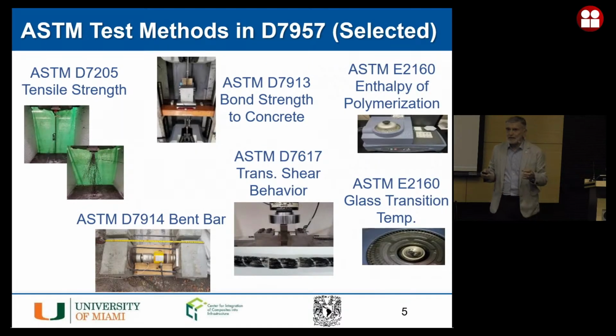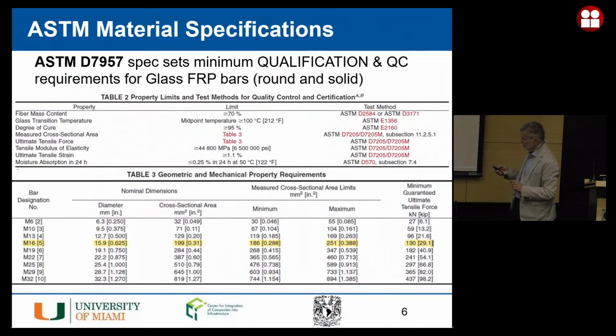In terms of quality assurance, if we follow this ASTM D7957, we run tests that are different from the ones that you might see in the laboratory. I'll give you an example of only one, this E2160. This is to measure the enthalpy of polymerization. What are we talking about here? What we need to do is to make sure that the resin is fully polymerized. If we don't reach at least 95 to 99% polymerization when the bar exits the pultrusion machine, we will not have the durability that we expect. So this is one of the tests that we run, and a specification of the standard tells us what is the range that is acceptable.